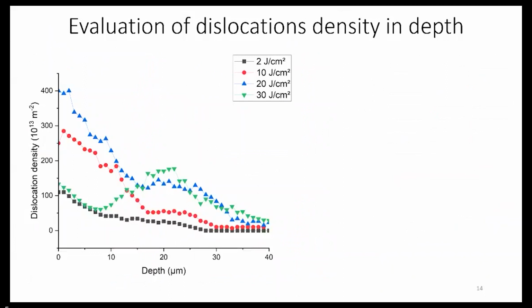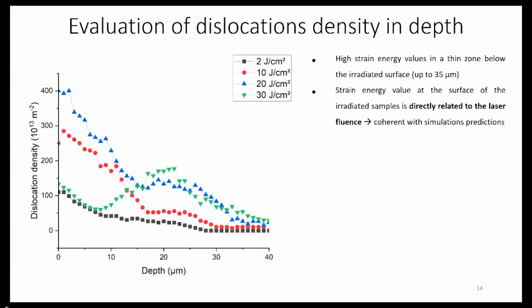These are results from the measurements I spoke about, done at the synchrotron, where we can see the evaluation of the dislocation density below the irradiated surface. What we can notice, and which is coherent with what we saw in the simulation results, is that when we increase the fluence, just below the surface, we increase the dislocation density. This is true for the first three fluences. And what we can see is that there is a different behavior at very high fluence.